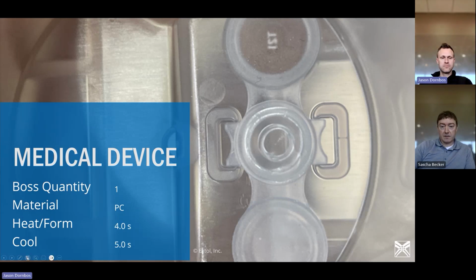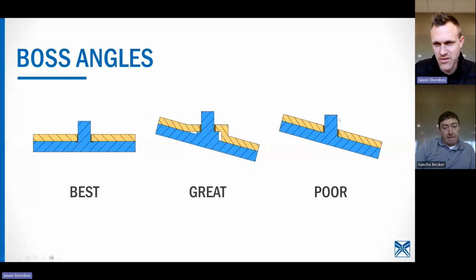Trying to think what we could do, like a Santoprene type of material. Yep, something like that. There's kind of 2 things. You can have it if your boss is part of something flexible. We've had applications where that's the case and you're staking it. Kind of ignore that. I mean, this is showing bad boss angles and a bad joint design, but look over here on the best side. And so here's my boss, and the yellow is showing my mating component. If the blue is a flexible material and you form this into a stake, well, the stake head is also going to be sort of flexible. So it probably won't be a very strong joint.